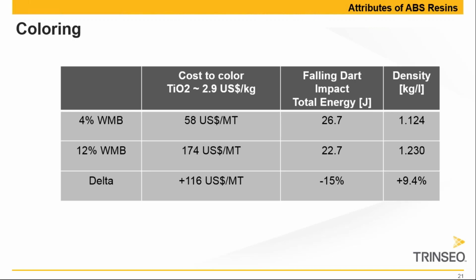Now, the extra dollars is not the only disadvantage. There is also some loss in physical properties, as you can see in the second column of the table, where we did some falling dart impact tests, and you see there is a 15% reduction in total energy measurement. So there is some loss in impact due to the addition of extra coloring master batch. And also, as titanium dioxide is a kind of mineral, your density will go up as well, and it's not negligible. It's about 9%. If you're looking at weight savings, then 9% is for sure not negligible.